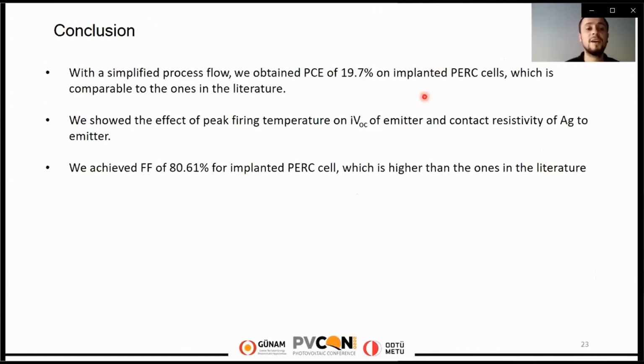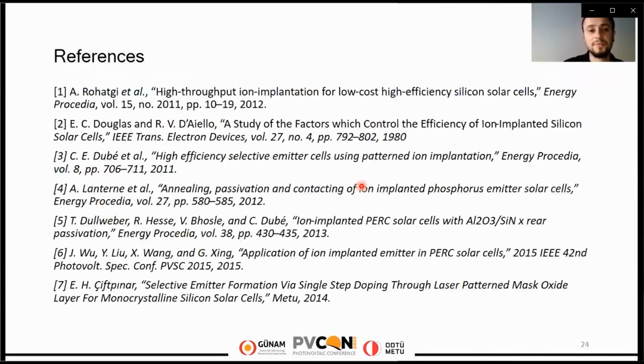In summary, we can say that with its simplified process flow, we obtained 19.7% power conversion efficiency on implanted PERC cells, which is comparable to the ones in the literature. We also showed the effect of firing temperature on the implied VOC of the emitter and the contact resistivity of silver to emitter. Finally, we achieved a fill factor of 80.61 for the implanted PERC cell, which is higher than the ones in the literature. And these are my references. Thank you for listening to my presentation.